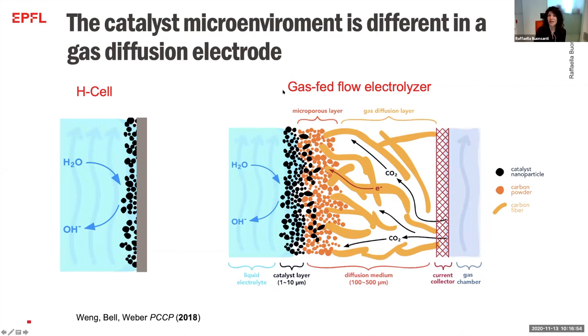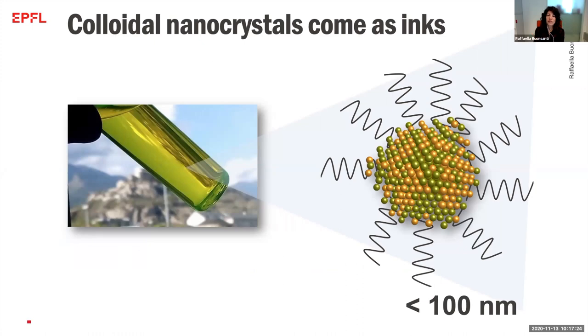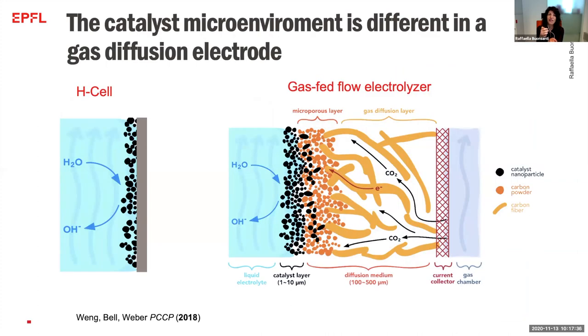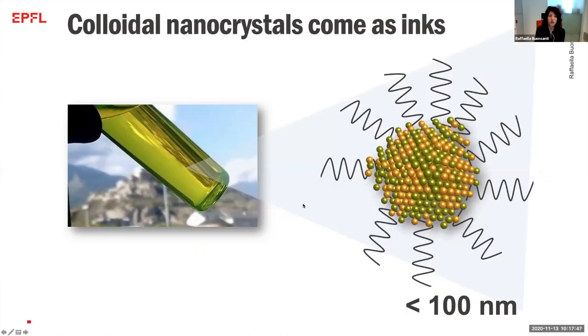Instead, when we move towards a gas-fed electrolyzer, the catalyst is deposited on what we call a gas diffusion layer, which is much more complicated. This means that the microenvironment around the catalyst, in terms of mass and electron transport, is really different. So we wanted to verify, in such a different environment, how much the intrinsic activity of the catalyst matters. Now, one thing to keep in mind about these colloidal nanocrystals is that they are constituted by an inorganic core, and then we have the ligands. These ligands make them soluble in a large variety of solvents. So now we basically have an ink, and we can easily take this ink and either deposit it on a flat glassy carbon in an H-cell, or integrate it in a gas diffusion layer. This is what my postdoc Gianluca did.